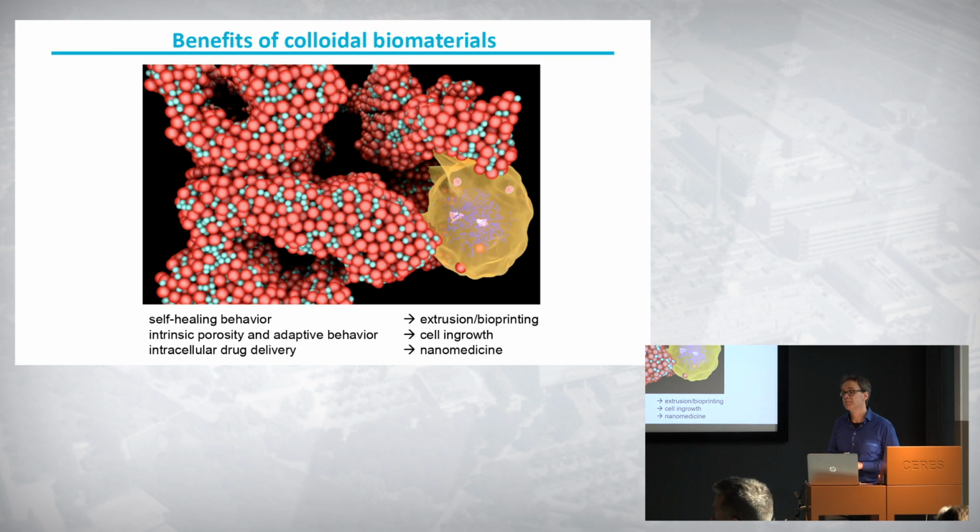Yeah, any other questions? Yeah, go ahead. First thing, gelatin tends to melt almost immediately at 37. So when it's in the particle shape like this, is it similar, does it melt almost immediately? No. I forgot to mention, but these particles are cross-linked, initially with glutaraldehyde, later on with more body-friendly, cytocompatible cross-linkers. You have to stabilize them indeed, otherwise it becomes a liquid pretty soon.